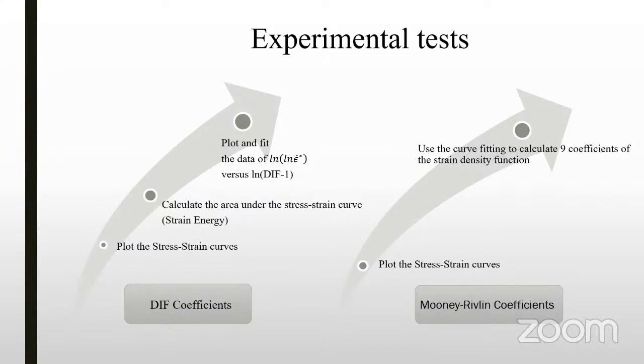In the other procedure, to calculate the Mooney-Rivlin coefficients, at first we need to plot the stress-strain curve, then we need to use curve fitting to calculate 9 coefficients of the strain density function.